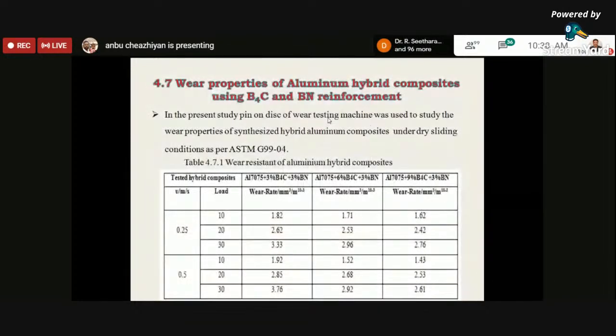So next we will go for wear properties of aluminum hybrid composites using boron carbide and boron nitride reinforcements. In that, a pin-on-disc wear testing machine was used under dry condition as per ASTM G99. A sample size of 6 mm diameter and 35 mm length is used, with EN31 steel as the counterface material, of surface roughness 0.3.